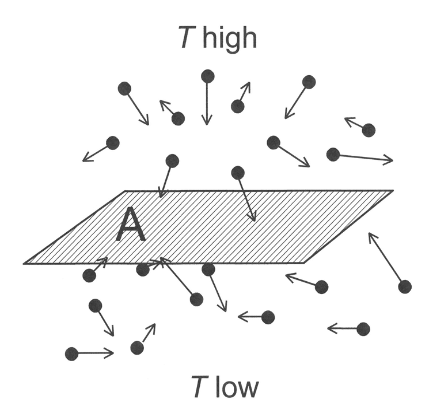On the other hand, heat conductivity in nonmetals is mainly due to lattice vibrations, phonons. Except for high-quality crystals at low temperatures, the phonon mean free path is reduced significantly at higher temperatures. Thus, the thermal conductivity of nonmetals is approximately constant at high temperatures. At low temperatures well below the Debye temperature, thermal conductivity decreases, as does the heat capacity, due to carrier scattering from defects at very low temperatures.